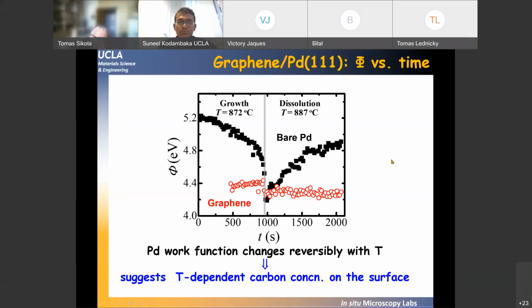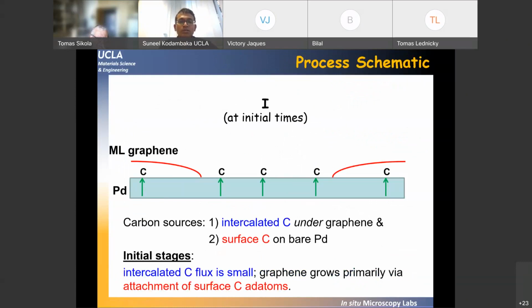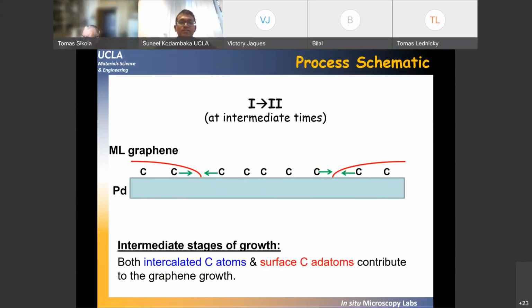Using this, we came up with a model for how graphene layers grow. Because the carbon has to segregate from the bulk to form graphene, you have two mechanisms that can contribute to the growth. Either the carbon atoms segregating onto the surface attach to an existing graphene island, or the carbon atoms intercalating under an existing layer also contribute to the growth of graphene. In the initial stages, it turns out that the attachment of carbon atoms to an existing island is the limiting step.